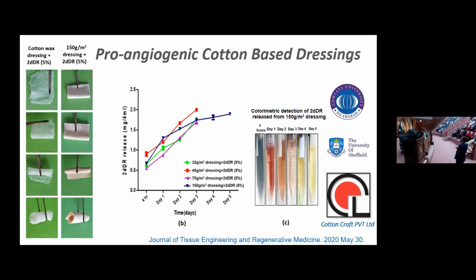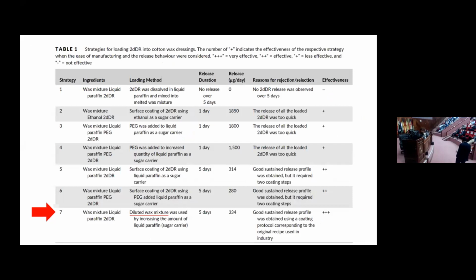We have seen that a 150 gram per meter squared, relatively thick fabric was suitable, and we have seen that this was able to release the 2-deoxy-D-ribose over 5 days of time. This is the Bials assay we use to detect how much 2-deoxy-D-ribose is being released, using a spectrophotometer. This table shows a lot of formulations, and not all formulations were good. Either we were seeing a quick release of the sugar within an hour, or we haven't seen any release. So ideally, we need a system which can give us the release from the dressings over a few days, because we need to change the dressing, for example, every week or every 3 days or something.